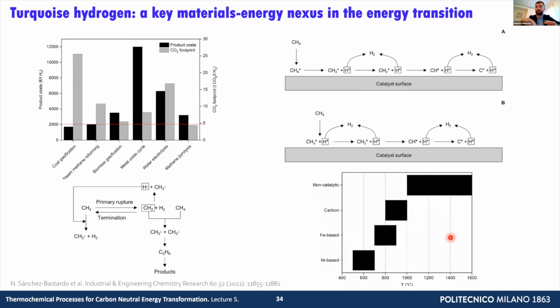Bottom right, you see the typical operating temperatures of non-catalytic pyrolysis, which is of course higher, and catalytic pyrolysis using carbon, iron-based, or nickel-based catalysts, which of course leads to a huge reduction in temperature associated with the lowering of the energy barrier due to the catalytic activity.